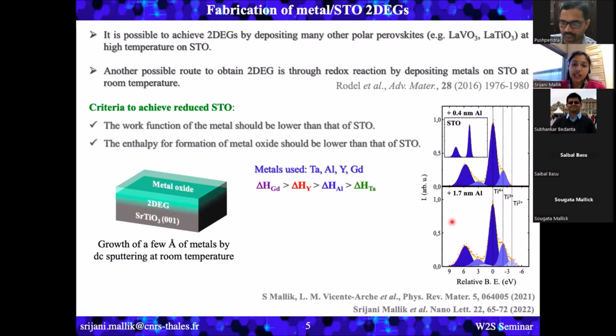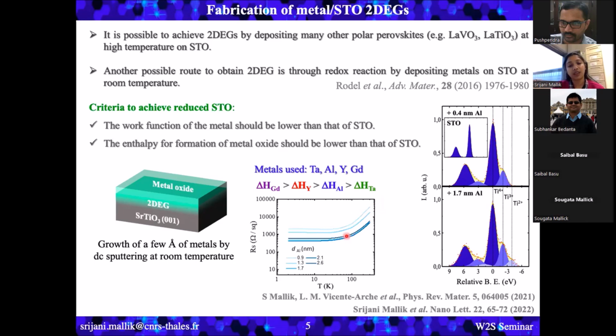So basically with all these metals, we could achieve the two-dimensional electron gas with STO. And from the transport measurements, we could see that all our samples are very nicely metallic down to very low temperature, that's 2 Kelvin. So if you are interested to know more about this kind of structures, then you can follow these 2 articles. Here you will get all the details related to this.